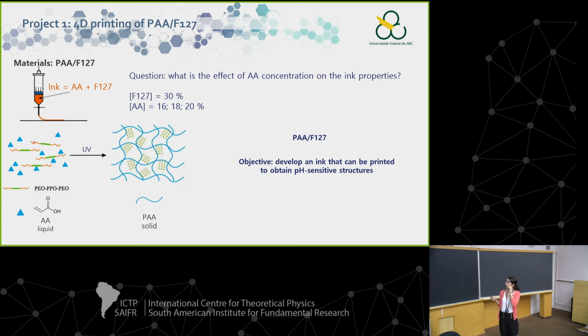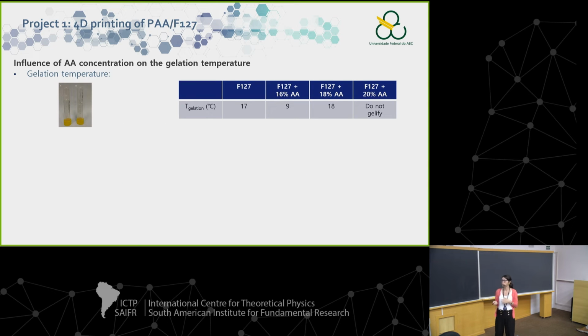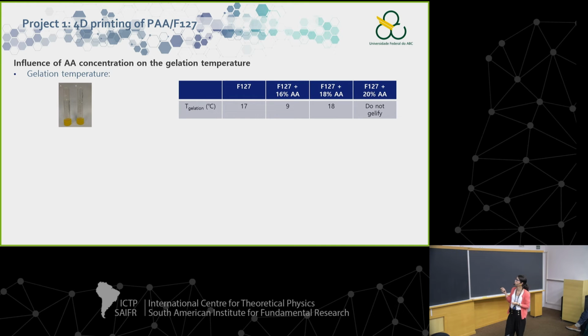But the question is, how much acrylic acid should we mix with Pluronic and keep the gelation properties and adequate rheological properties? So we fix the concentration of Pluronic and change the concentration of acrylic acid. The first test that we perform is very simple, a test of inverse tube. We place a small volume of the different compositions in a tube in a thermostated bath, and we increase the temperature of the bath step by step. At each temperature, we take the tube and reverse it. If it flows, it didn't gellify. If it doesn't flow, it gellifies. So we determine the gelation temperature.